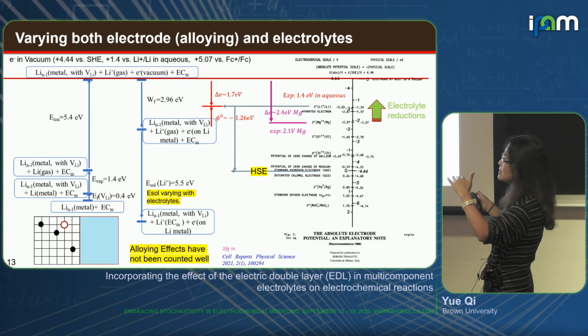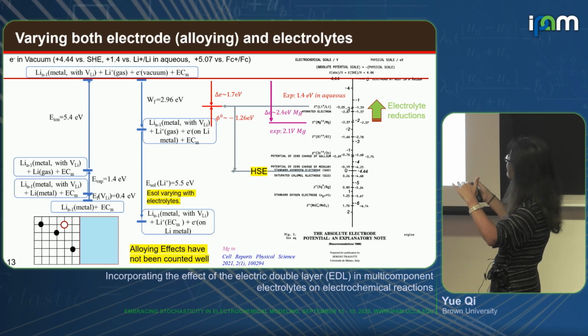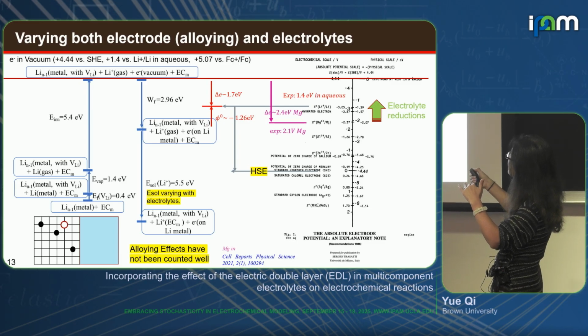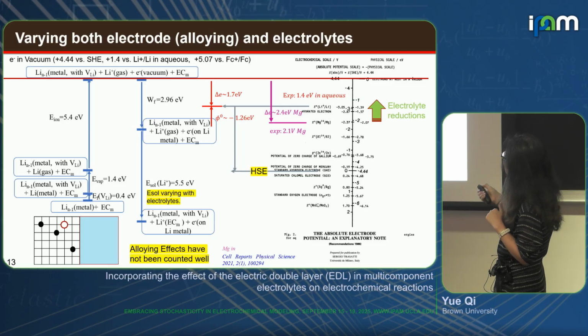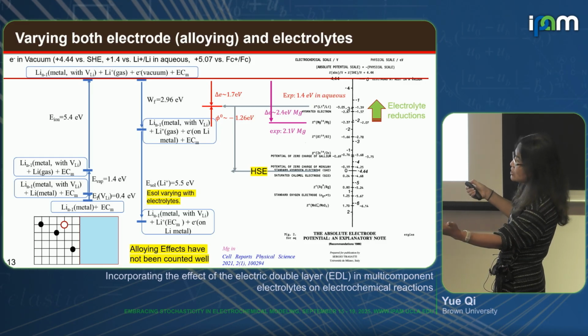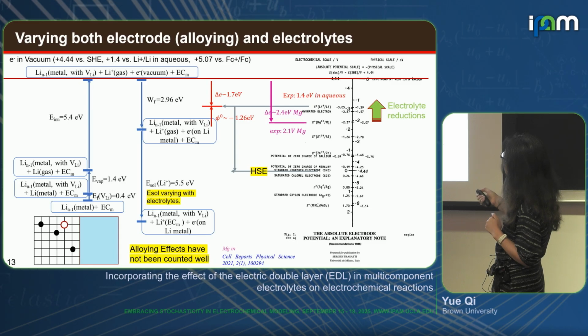Right, so this energy level, the Fermi level of electrons, is necessary for us to align with the electrolyte reduction voltage, right? So the electrolyte may start to react here, and therefore those will not be stable. If you're operating the battery at the lithium reduction voltage, the electrolyte will be reduced. If the electrolyte reduction voltage is above the lithium reduction voltage, then the electrolyte will survive. So this will allow us to really compare the reduction voltage of deposition and electrolyte decomposition.